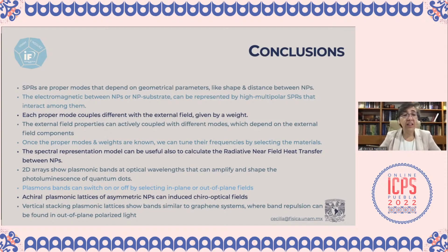Well, as I showed you, let's say as conclusions, the surface plasmon resonances are proper modes that depend on the geometrical parameters, the shape, the distance between nanoparticles, the presence of other nanoparticles, and the electromagnetic interaction between nanoparticles and substrate, and can be represented by high multipolar surface plasmon resonances. And each proper mode couples differently with the external field.